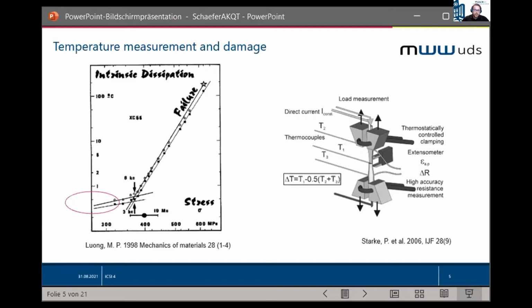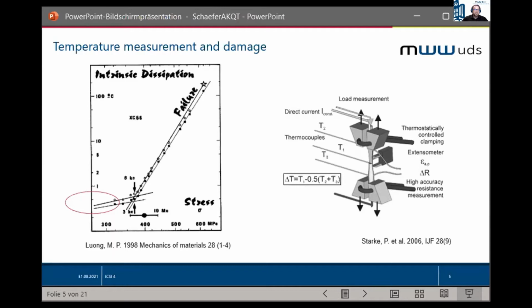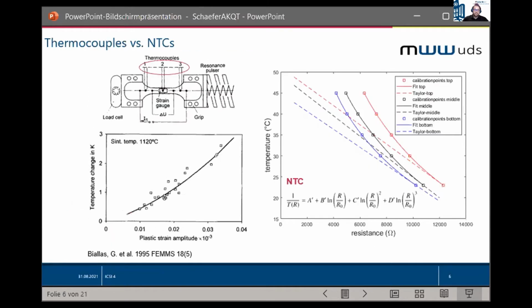We need to measure the heat generation inside the sample during fatigue. And to be honest, if the grips are tempered, the temperature represents the heat generation. But if we go to the fatigue limit, the heat generation is quite small. You can see it here on the left-hand side. It's below 1 degree C. And if we want to know what happens at this point, we need a very, very good resolution. And below the knee point, the temperature increase is in the range of the resolution limit of the infrared camera. And that's the challenge to deal with in this investigation.